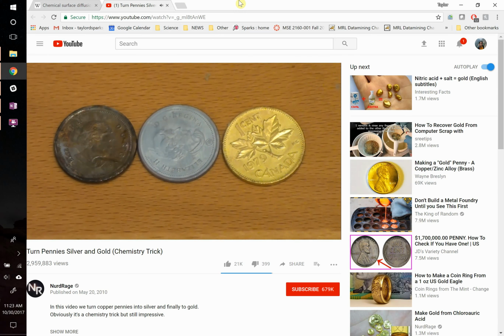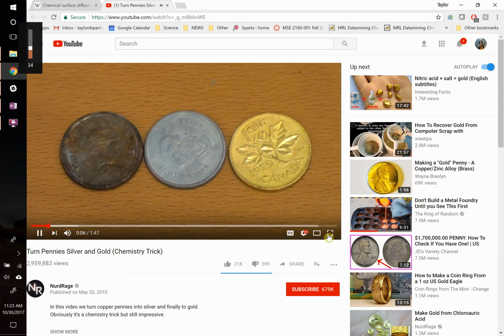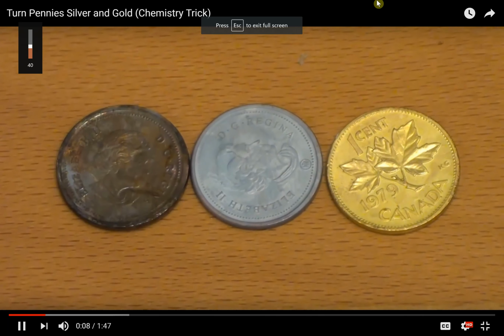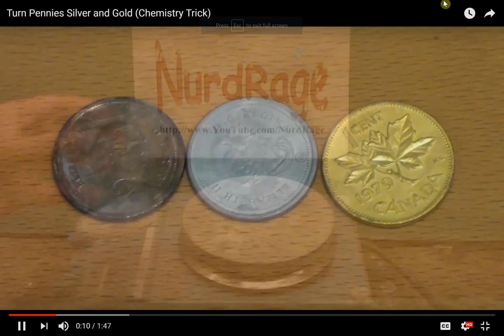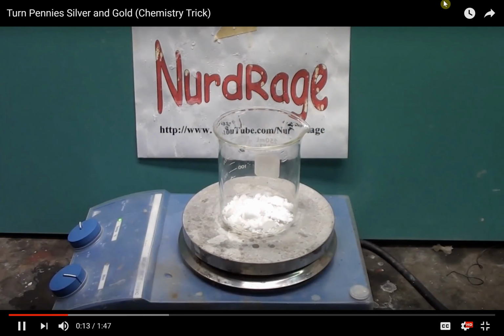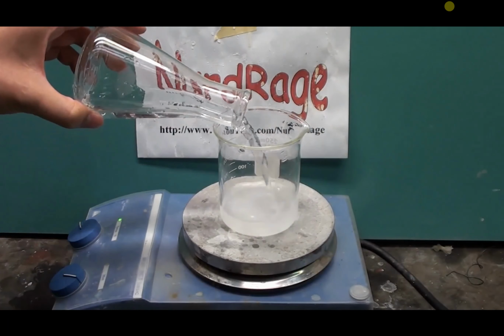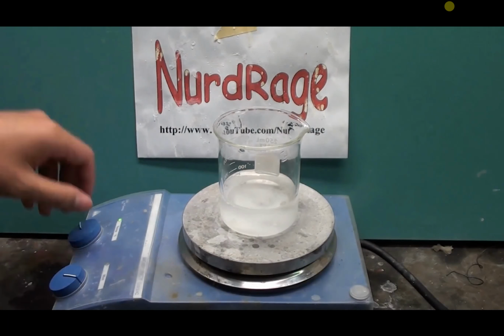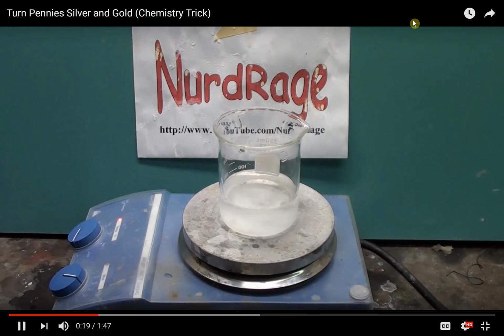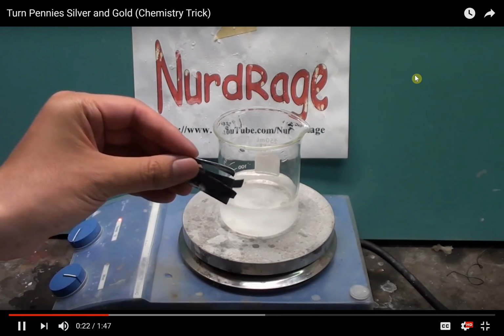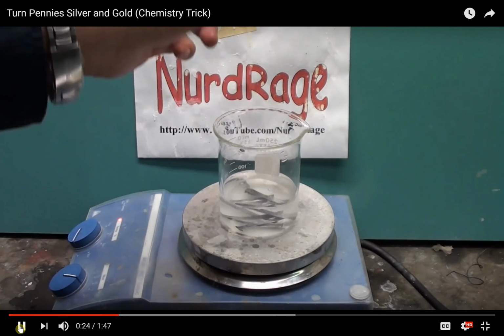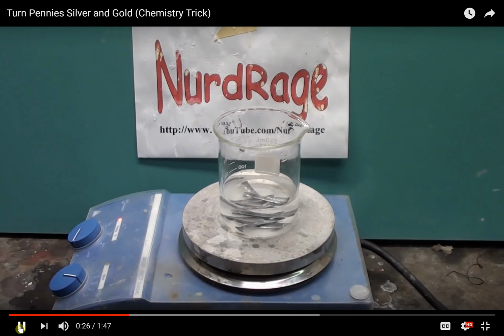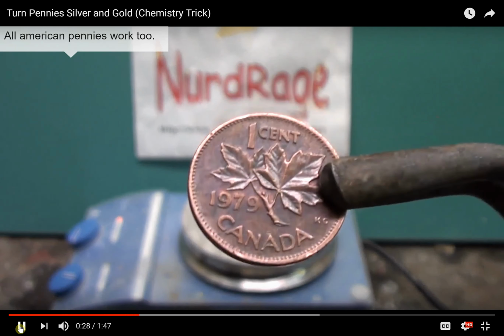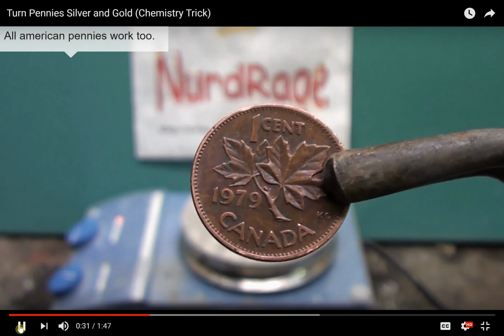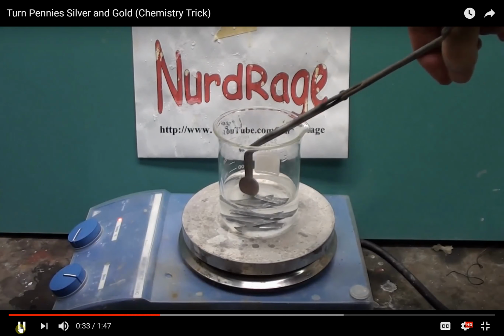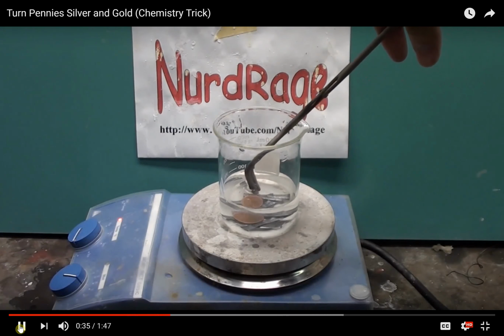Greetings, fellow nerds. In this video, we're going to perform the classic chemistry trick of turning pennies into silver and gold. First, get 30 grams of zinc sulfate. Then add 100 milliliters of water and turn on the heat to get to boil. As it's going, add in a few strips of solid zinc metal. Please check the video description for where I got my chemicals. Now get a copper penny, or any piece of clean copper for that matter, and drop it in. It has to touch the zinc metal for the reaction to occur.